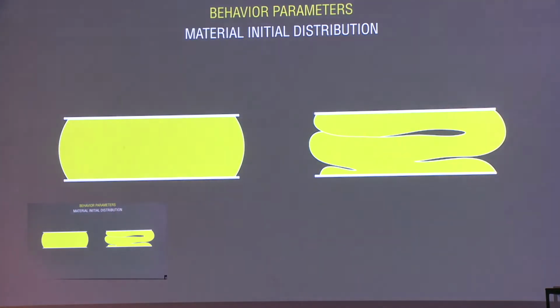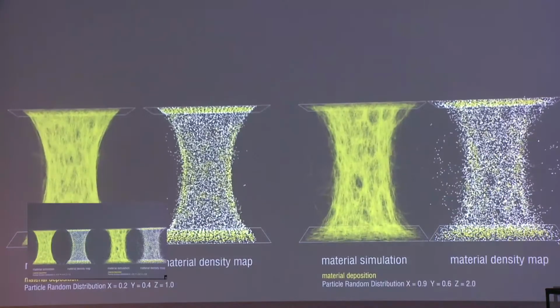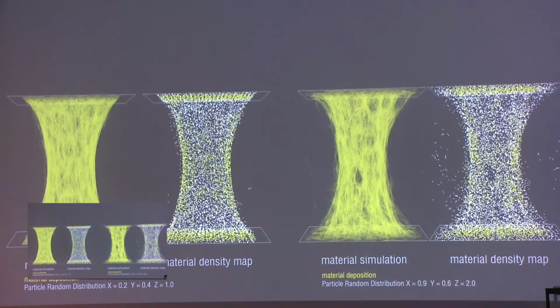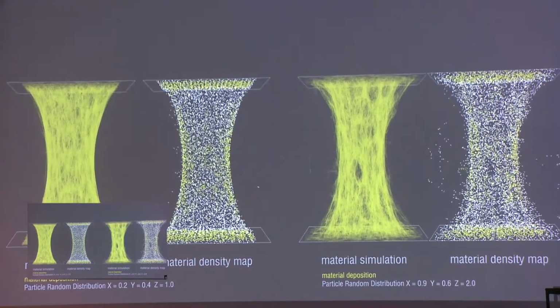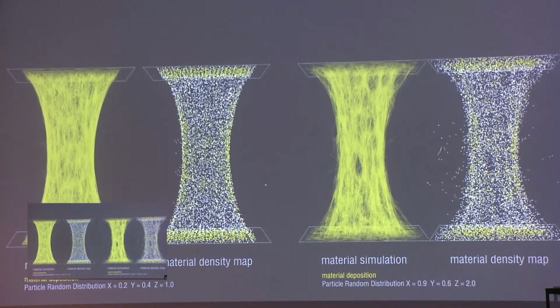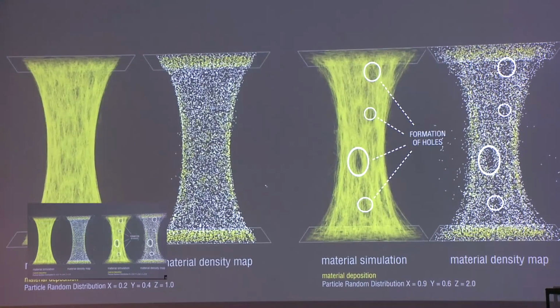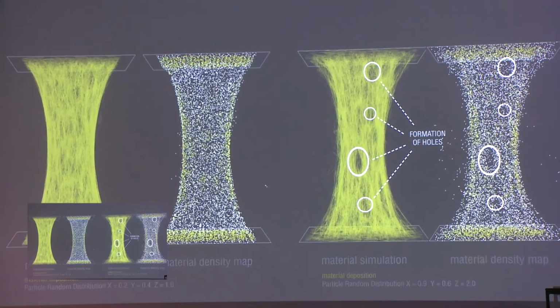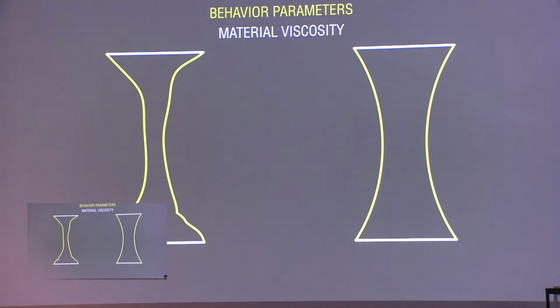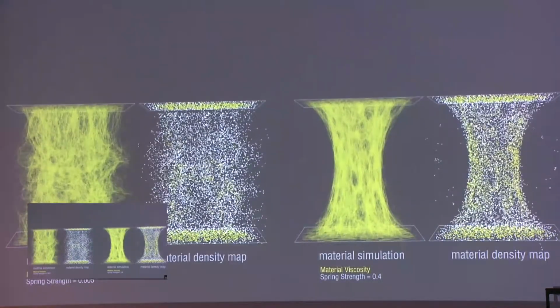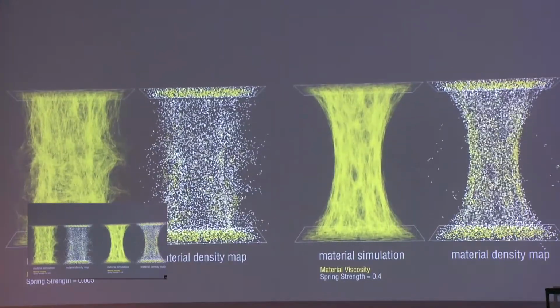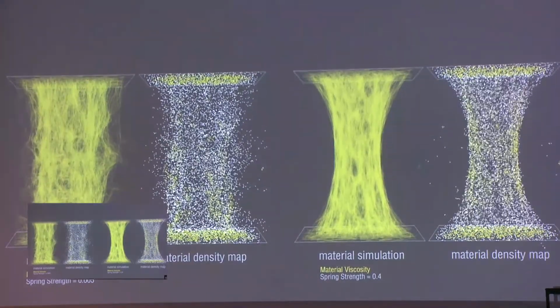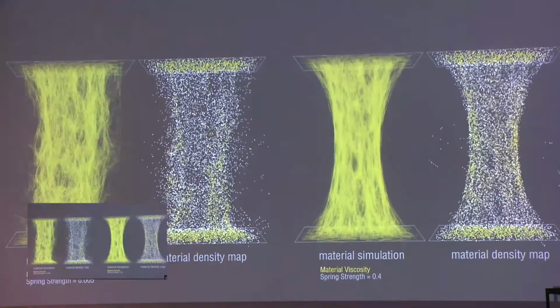Another important parameter is the initial material distribution that controls the amount of holes that we generate in the beams. We can see on the right side the formation of holes, while the left side is uniform and doesn't have holes. The last parameter that we studied is the viscosity of the material. The denser parts have more weight and they collapse on themselves. This doesn't allow the section to form properly.